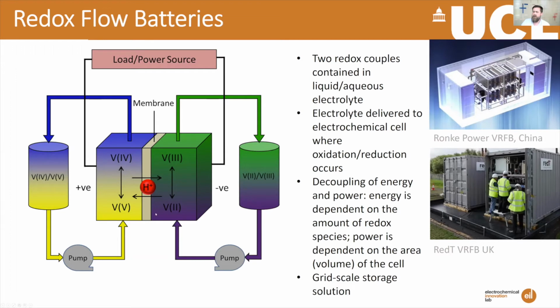The vanadium chemistry is the most widely established in terms of the industry, but the high cost of vanadium is meaning that people need to look away from this now a little bit. One of the key benefits of the vanadium technology is, of course, you've got vanadium species on both sides. Crossover between the two electrolytes is actually a bit of a problem. When it happens in vanadium, at least you're just putting vanadium into vanadium, and so you can electrochemically regenerate the cell. Whereas if you were crossing over zinc or something, then you'd actually end up poisoning the cell.